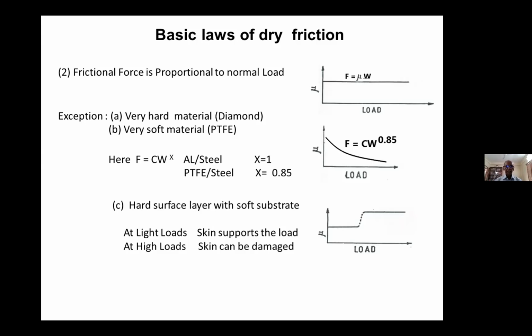Experiment shows that for sliding of PTFE against steel, this x is equal to 0.85. And we do not get a constant coefficient of friction, as shown in the picture.